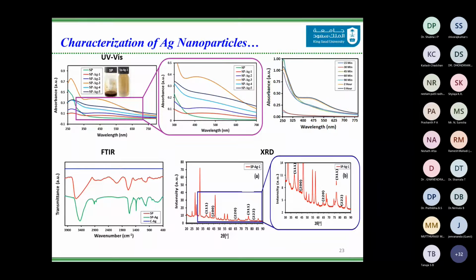Moving ahead, when we did XRD of this particular compound, we found all the peaks relevant to the silver nanoparticles. However, we also found additional peaks. These additional peaks had baffled us as to what they were. And in the later slides, I will show you what it turned out to be.